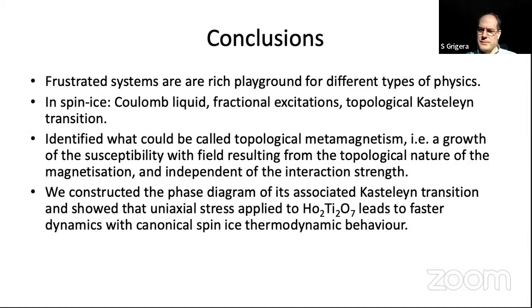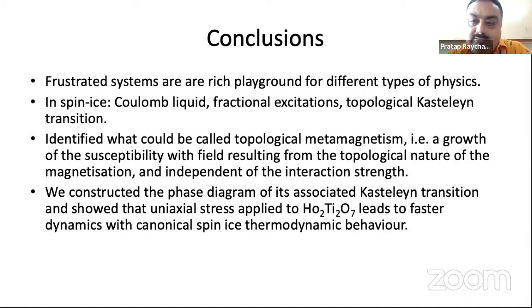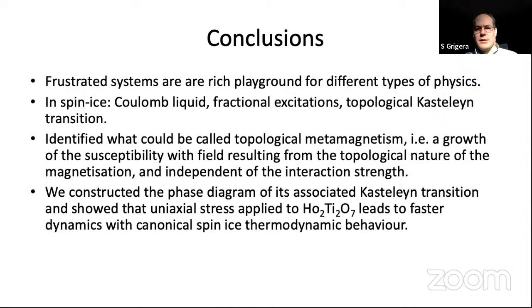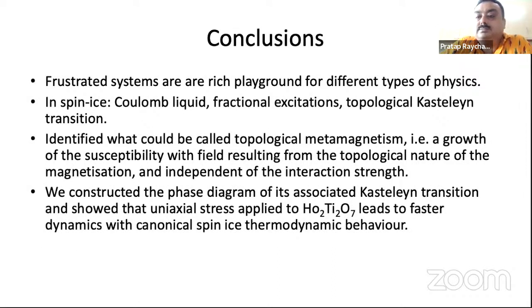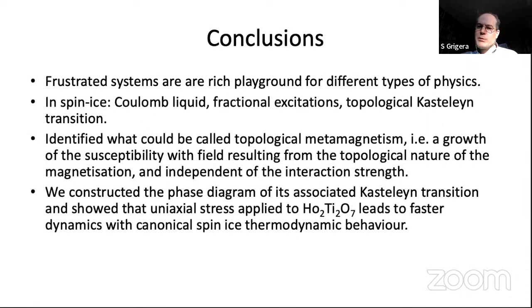But when you say it freezes, does that mean it orders or it freezes disordered? No, it freezes completely disordered. As a matter of fact, like ice, we've done these experiments where we cool the sample very slowly for a whole month, and did neutron experiments before and after, and we see absolutely no difference.